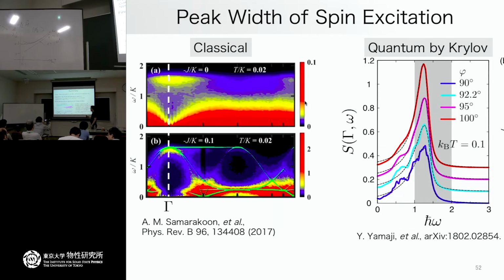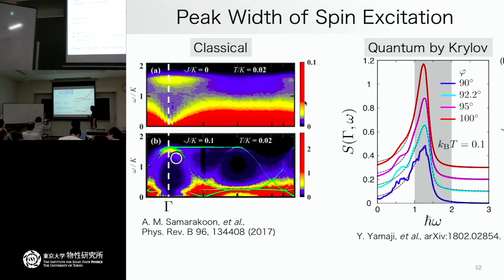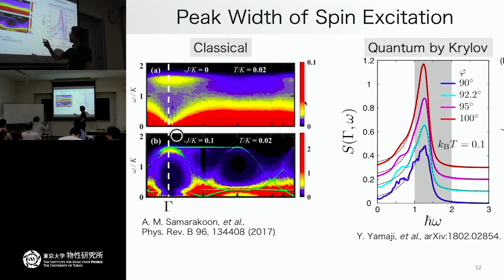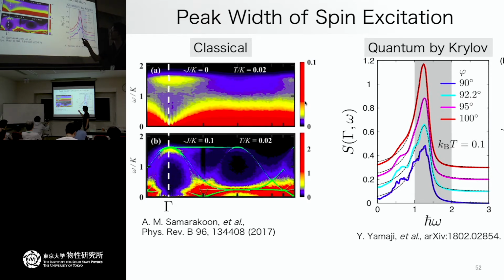Okay. For this system it is really convenient because from the classical analysis, we know that we have a broad peak structure at the gamma point, and that this broad peak should cross over to the magnon dispersion. So I choose this point because in the Kitaev limit we have a continuum here, but in the magnetically ordered phases, this should go to the magnon dispersion. But even in magnetically ordered states it's located at high energies, so the magnon should damp.